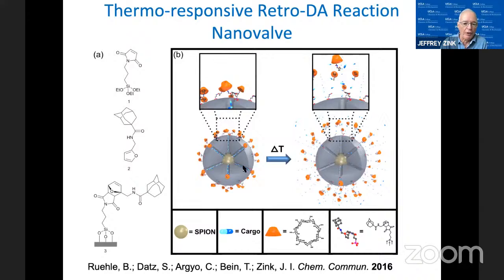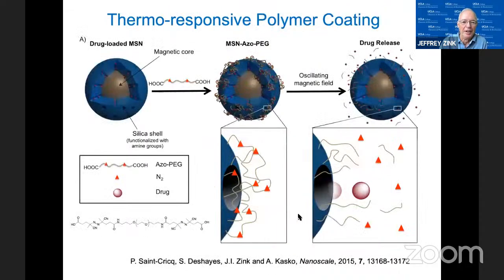One of the early ones that we looked at uses the retro-Diels-Alder reaction. Diels-Alder reaction is thermosensitive. So at low temperatures, we could put a very bulky adamantane cyclodextrin type cap on the whole thing. That's just a big capping system. But under higher temperatures, the retro-Diels-Alder breaks that bond. It's a snap type, if you will. The top comes off and the drug can be released. So that was one of the early types of caps that we used.